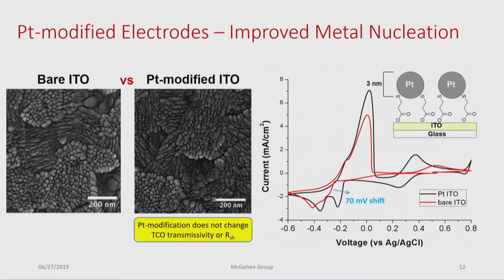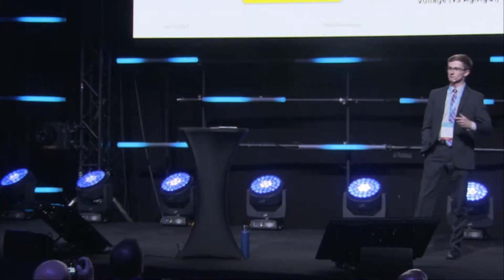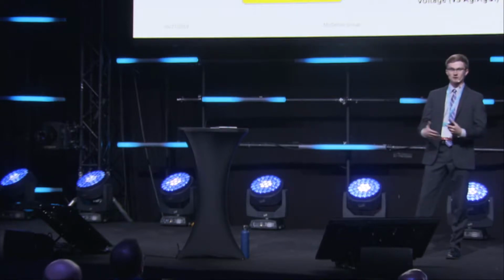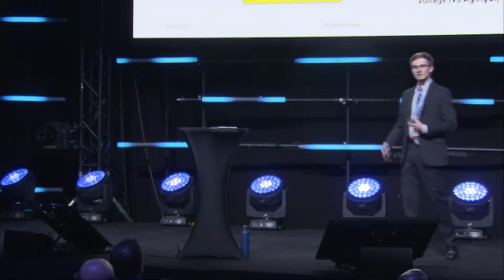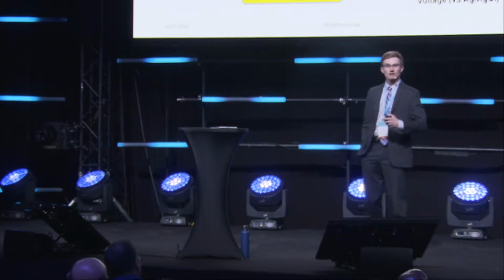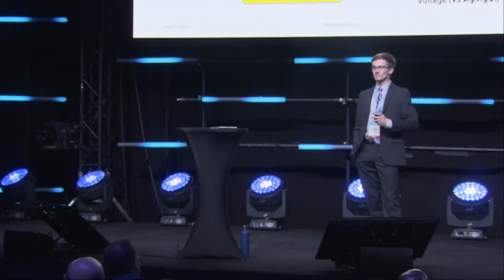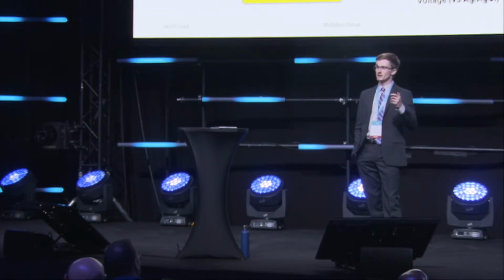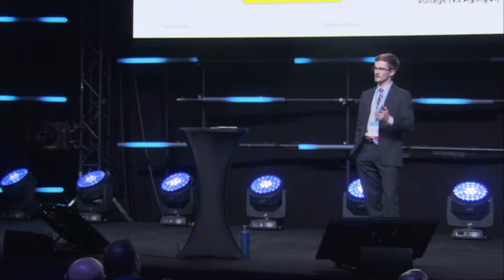So we don't have a complete conformal film of platinum, so we're really not using much material. Additionally, this platinum modification does not change the transmissivity of the TCO, and it also does not affect the sheet resistance, which is great. So keep in mind what we were trying to prove. We want these platinum nanoparticles to improve the metal nucleation on our TCO. So the way that we went about testing this is we ran 3 electrode half-cell experiments on a bare ITO and a platinum-modified ITO surface.